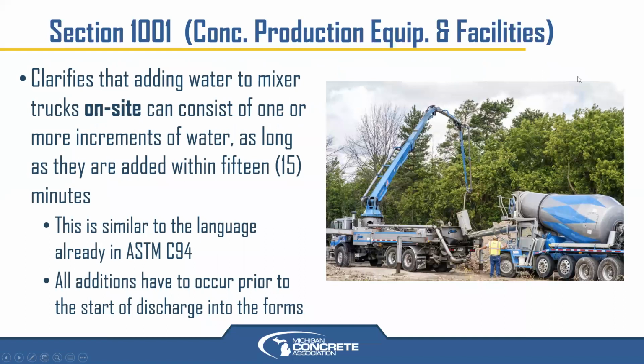Another, again, slight change, but may help with some confusion and discussion and disagreement on projects in the field, is that they've clarified and added some more language on adding water to a mixer on site. You can adjust a mixer on site when it pulls up and it's low on slump or has low water cement ratio and you're not bumping up against your maximum water cement ratio yet. You can do that in multiple increments, as long as they're added within 15 minutes of each other and mixed in. This is similar to what is already in ASTM C94, very similar. I think it's almost the same language.